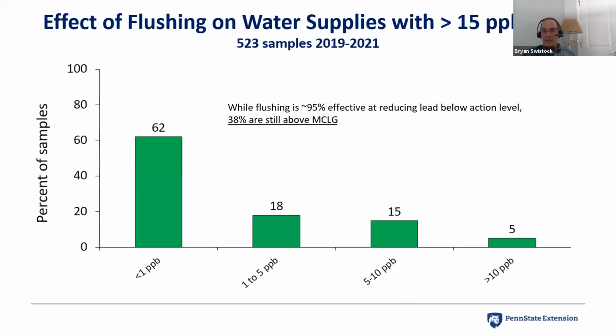But there is an important caveat with this. Not only are we not addressing that corrosion problem and the damage done to the plumbing system, we also have to look at how much we are able to reduce that lead down by flushing the sample. So this, again, is looking specifically at samples where the lead level was above 15 parts per billion in the first draw, and then we flush the sample out for 1 minute. What is the resulting running water lead concentration? And in 62% of the cases, the resulting lead was below detection, less than 1 part per billion, which is good. But the problem is 38% of the cases still had detectable amounts of lead.